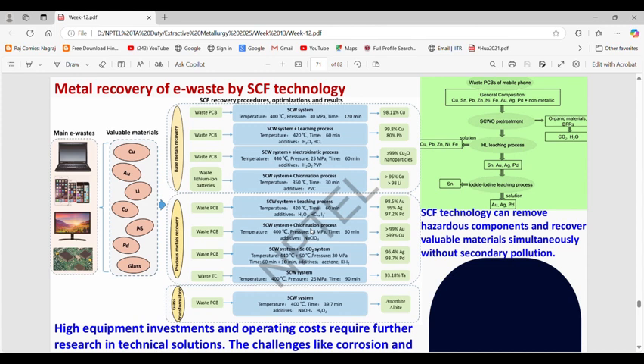Then coming to the precious metals recoveries from these waste PCBs, some researchers have recovered gold, silver, palladium, and tantalum via a supercritical water system at a temperature of around 400 degrees Celsius and a pressure range of around 20 to 30 megapascal. With the help of this supercritical water system, they have recovered a major amount of precious metals present in the waste PCB boards or waste tantalum capacitors.